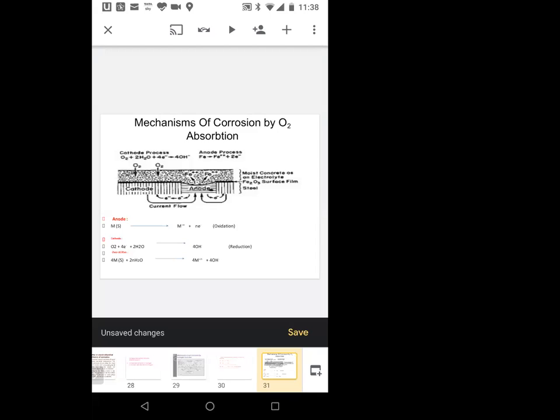at that part, the metal will be exposed to the neutral solution. And that small part will be acting as anode. And oxidation takes place at anode. Electrons will be released from the small area and pass through the core metal to the remaining surface of the metal. And from there, the electrons come out, and the electrons are taken by the oxygen in the dissolved state in the neutral solution or in the water. And that oxygen takes the electrons in the presence of water to give rise to hydroxide ions. These hydroxide ions will react with the metal ions to form the metal hydroxide.